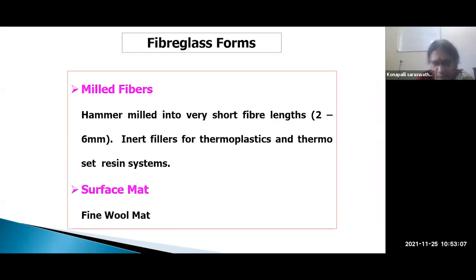Then milled fibers. Milled means hammer milled into very short fiber lengths, almost 2 to 6 mm. These are added as filler materials in the composites. These are the milled fibers. And surface mat. It is a fine wool mat. Like in our ovens, if you see, fine glass wool will be kept as insulation in insulation panels.